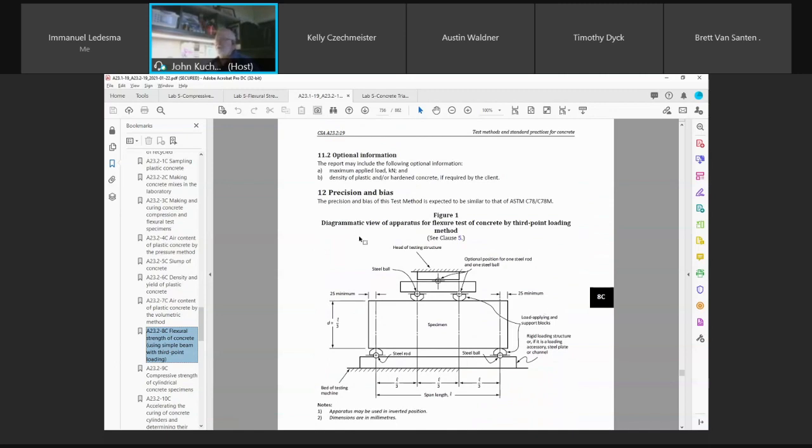Here's the setup that we would do. This is a flexural setup that you would see at CSA. You've got knife edges here, or supports. You slide the beam in, and the beam is long enough that you should have at least 25 millimeter overhang from the supporting rockers, and you're applying the load. It's two loads. So this is third-point loading, believe it or not, but it's distributed, so the load comes through.